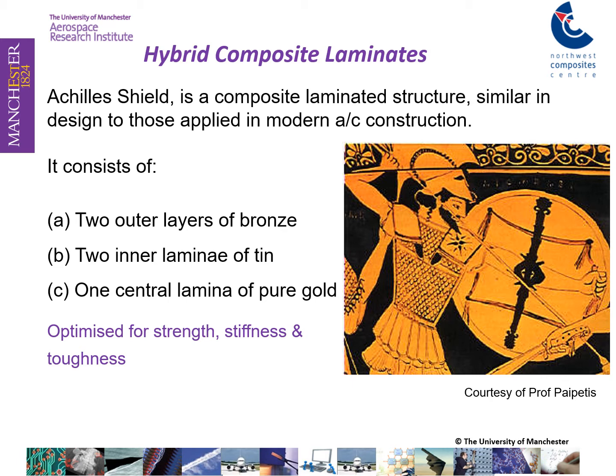And then we talk about hybrid layered structures that enable us to optimize the strength, stiffness, and toughness properties. And here we see an example that goes back more than 2,000 years ago for the Achilles shield, where the designer introduces a layered construction which is very similar in design to those applied in modern aircraft fabrication. And the shield consists of two outer layers of bronze, two inner plies of tin, and one central lamina of pure gold. The combination of these three different materials enables building a structure that is strong, it is stiff, and under an impact event, it doesn't shatter. It provides toughness. It demonstrates damage tolerance.